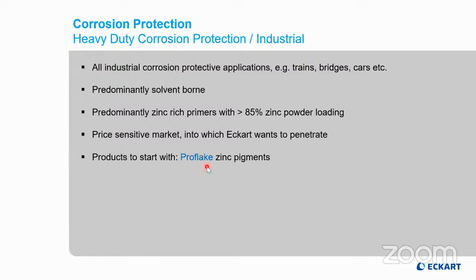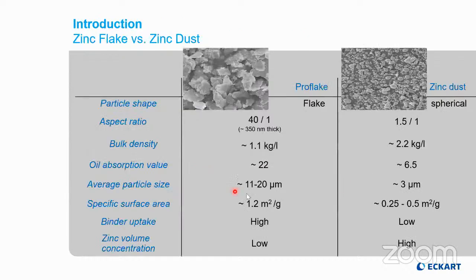And our ZincFLAKE products are called ProFlake. ProFlake is an abbreviation standing for protective flakes. So instead of what you are used to in the standard zinc-rich primers as a corrosion protective system, where zinc dust is used, which is a spherical species with a relatively low surface area, a very small average particle size, meaning 3 microns average, and a small oil absorption value, our offering is ProFlake, a flake-shaped zinc particle with a substantially higher oil absorption value, meaning a substantially higher specific surface and a higher binder uptake.